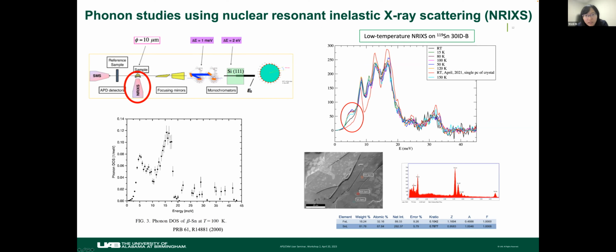We did SEM, and we found there is an excess of tin, mostly on the surface. So we contacted our sample grower, and they mentioned there could be excess tin because the sample was made using tin as a flux. And then we looked into this paper, also done on NRIXS, on beta tin, the phonon density of states at low temperature, and there is clearly a mode around 5 milli-electron volts. So we conclude that this inconsistency around 5 milli-electron volts could come from the excess tin on the samples that we studied.